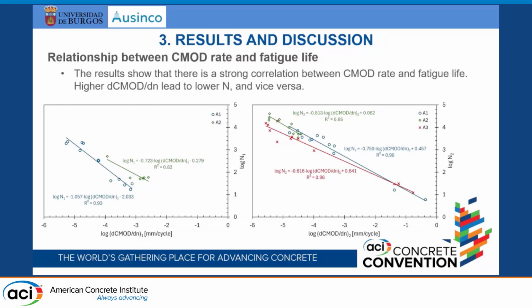What we can see here, we only have A2 and A1 in this part, okay? So in the one corresponding to the matrix fatigue, because in A3 there is no matrix fatigue. And here we have the three series, because in all the three series we have the red line, the one corresponding to fiber-matrix bond fatigue. There is a very strong correlation between the CMOD rate of each mechanism and the number of cycles corresponding to that mechanism, around 0.9 of R square coefficient.